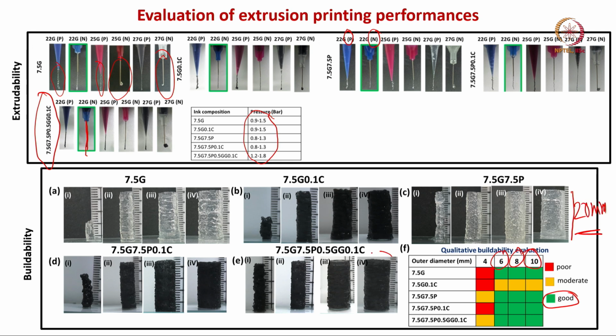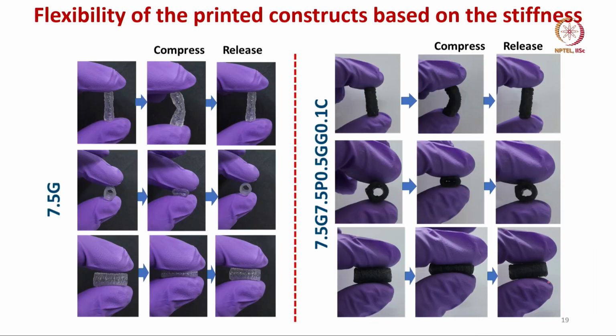So, you can see that 7.5 GELMA, 7.5 PEGDA, 0.5% Gellan gum, 0.1% carbon nanofibers also gives very stable cylindrical nerve conduit structures, but that was not the case when you use, for example, 7.5% GELMA with 4 millimeter outer diameter. So, the red one is not acceptable, the green one is what is acceptable.